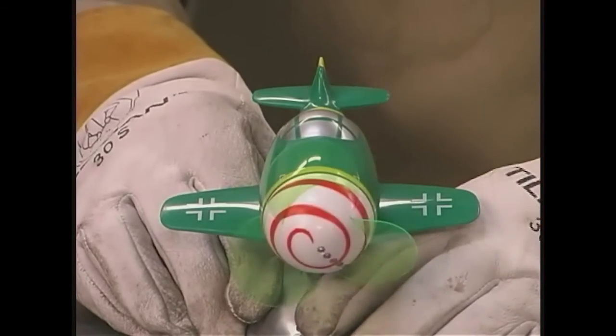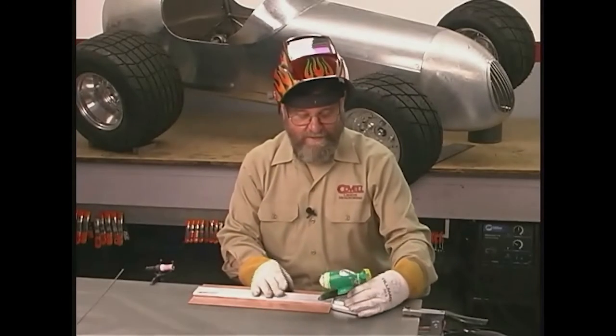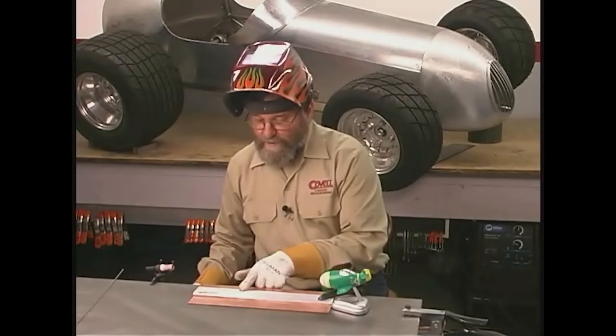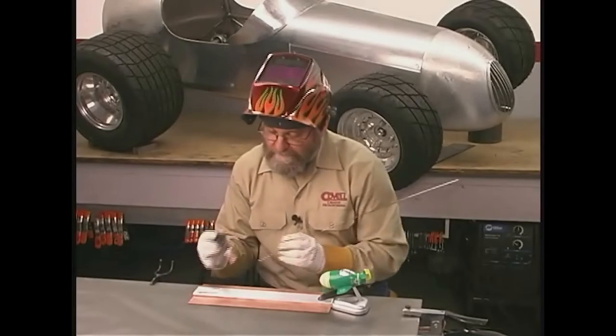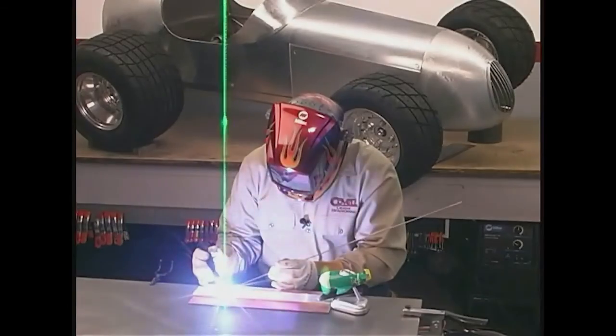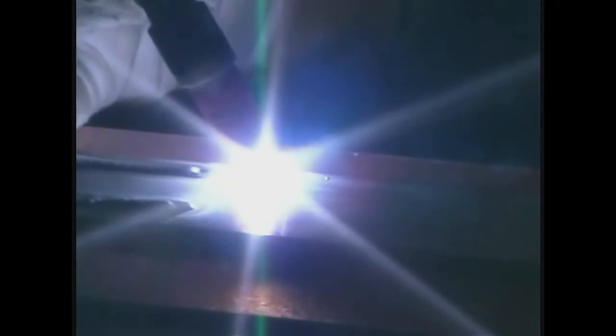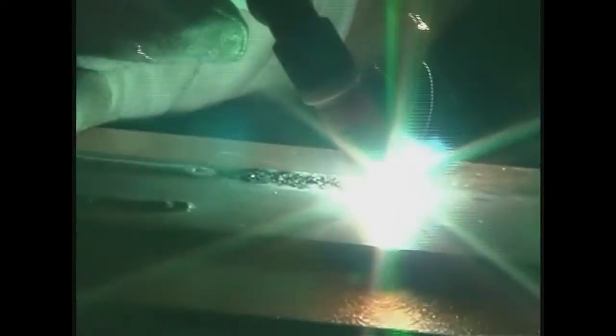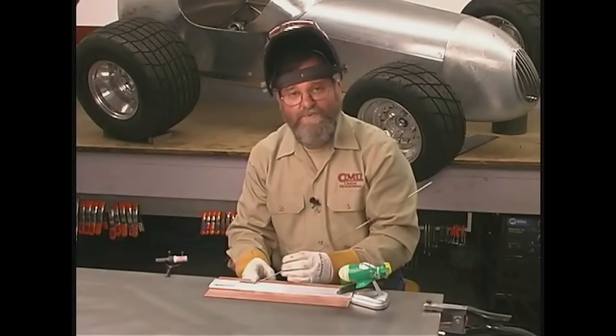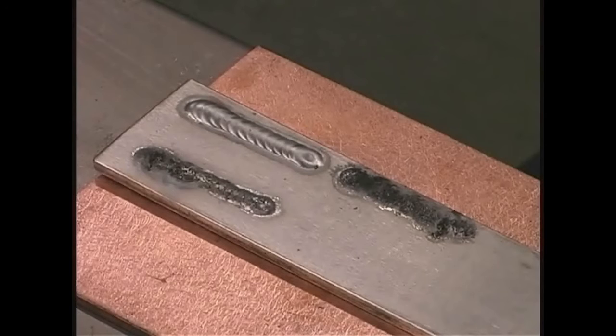So I've set the flow meter back to 18 cubic feet per hour, but as I'm making this weld, I'm going to turn on this little toy fan, and you'll see that it's just going to blow away the shielding gas. So I'll put the fan right over here, turn it on, and then I'll make a weld right next to our first weld. Okay, when you take a close look at this weld, you'll see it's even crummier looking than the one we did with 9 cubic feet per hour of argon flow. And this was done at 18 cubic feet per hour.